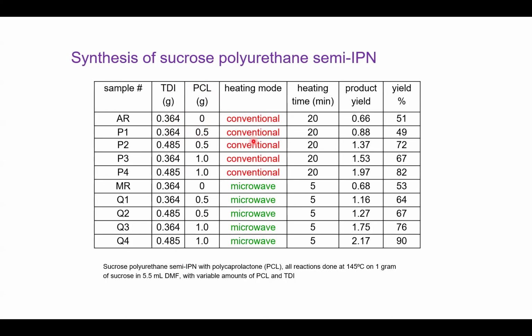We're done with conventional heat and microwave. Conventional heat takes 20 minutes, microwave 5 minutes. So again, saving time and energy using microwave. And the yields are very, very similar. If anything, microwave is slightly higher because you heat so fast, you can force them to get together. There's no time for phase separation. So again, saving time, energy, and getting the same product.